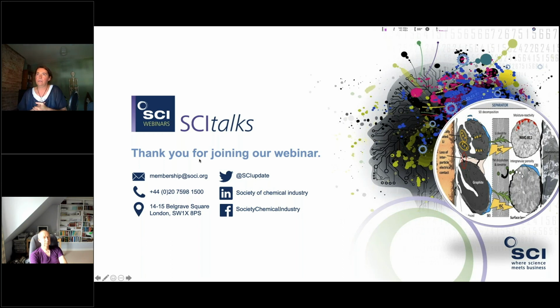But you know, the formation of SEI and CEI are actually quite important. And so if the binder totally encapsulated every particle, batteries wouldn't work as quickly as they do. So it's a bit of a compromise between surface anchoring, but allowing sufficient SEI to get that passivity, if that makes sense.